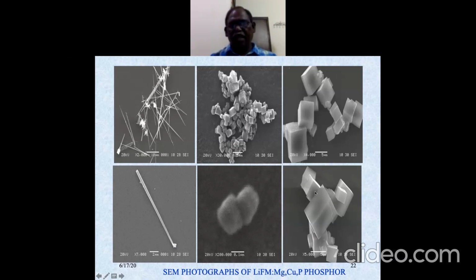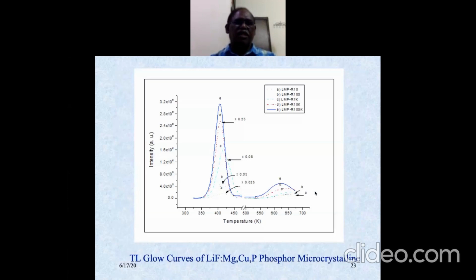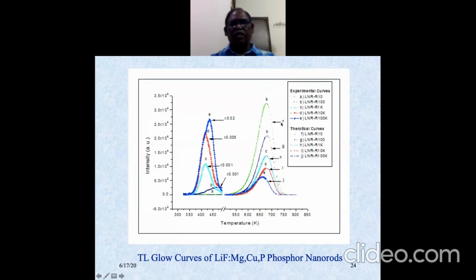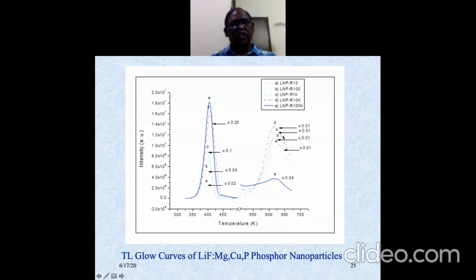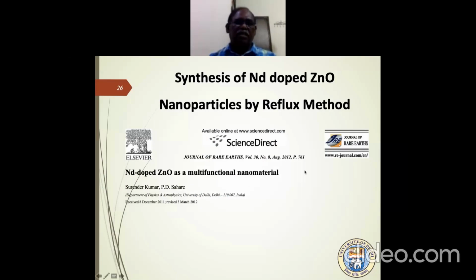We studied these luminescence characteristics, and you'll see that the glow curve structures change by changing the morphology as well as by changing the particle size. So this is for microcrystalline, this is for nanorods, and this is for nanoparticles. It changes maybe because of some crystal field effect, or because in this nano form some little change occurs and the properties get enhanced, and these kinds of things we could not study in microcrystalline. So in materials, it's not only from an application point of view but also for studying different properties. We had the same experience studying the effect of phase change on these luminescence properties. Then we also studied some ZnO:Nd, and this is by the reflux method.